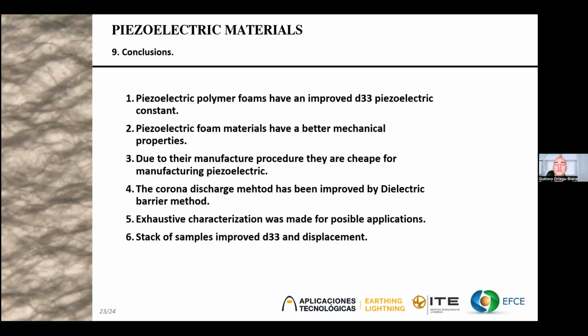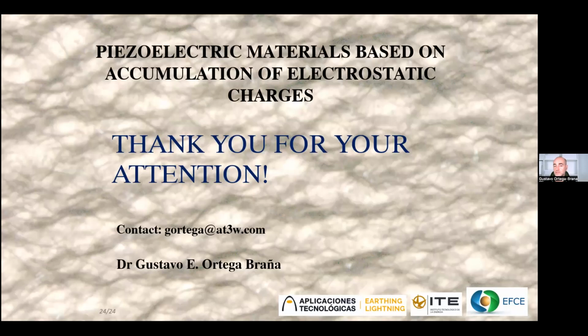Finally, concluding, piezoelectric polymer foam has an improved d33 piezoelectric constant. Piezoelectric foam material has better mechanical properties. Due to their manufacturing procedure, they are cheap to manufacture. The corona discharge method has been improved by the dielectric barrier method. Exhaustive characterization was made for possible applications, and a stack of samples improved d33 and displacement for this material. And that's all. I'm finished.